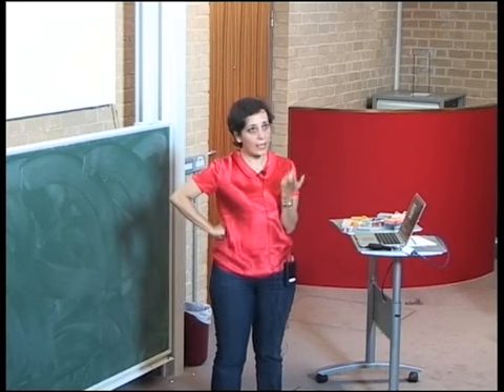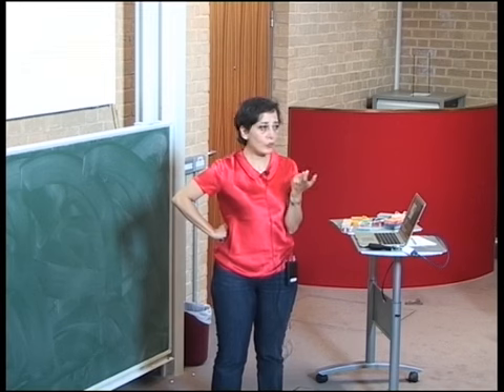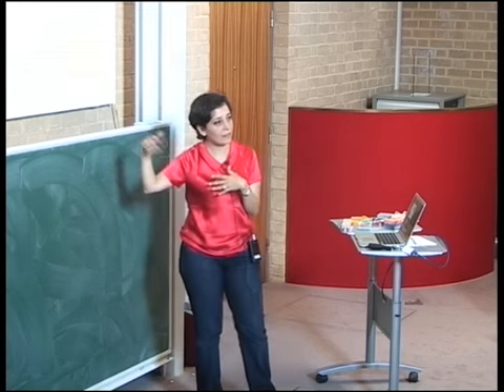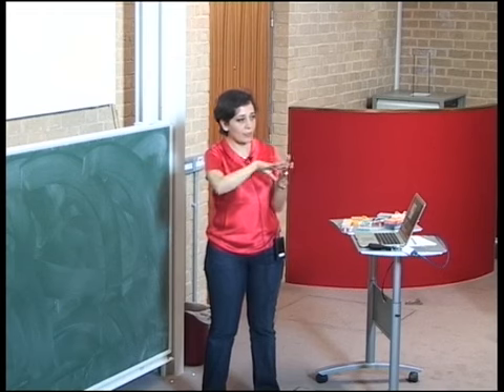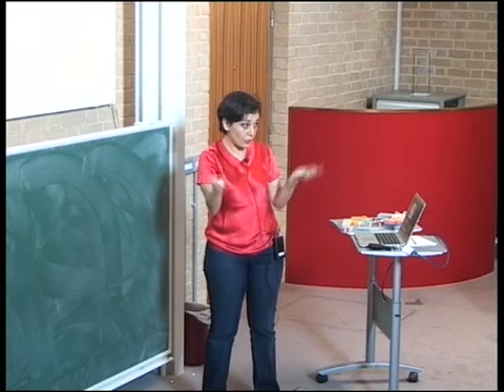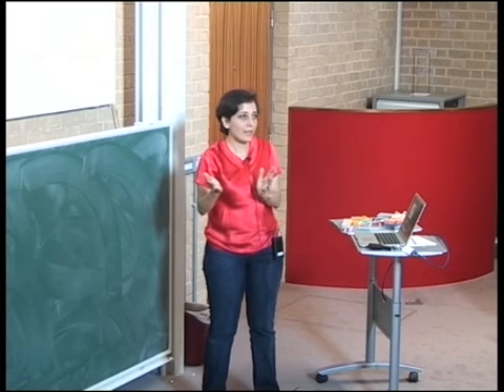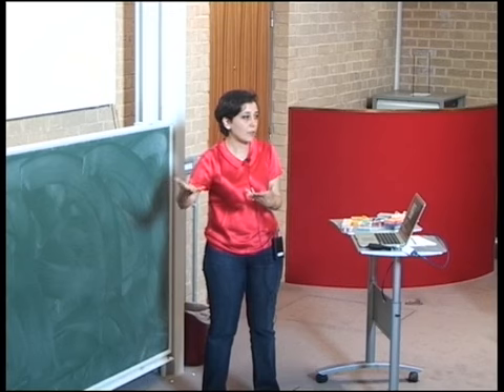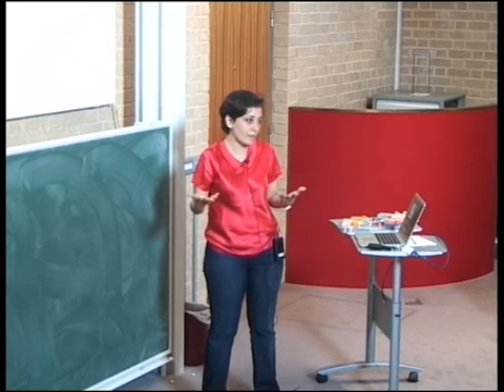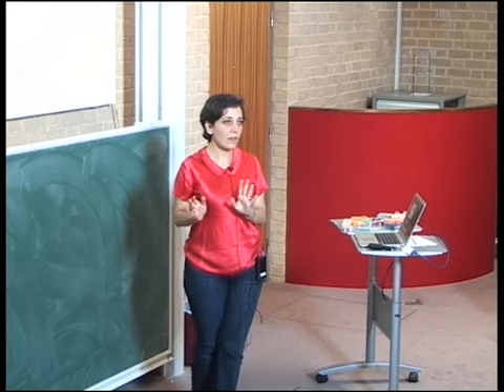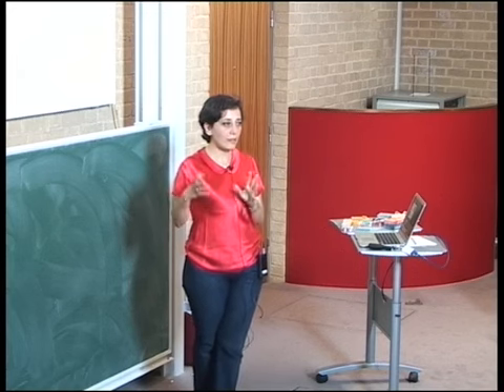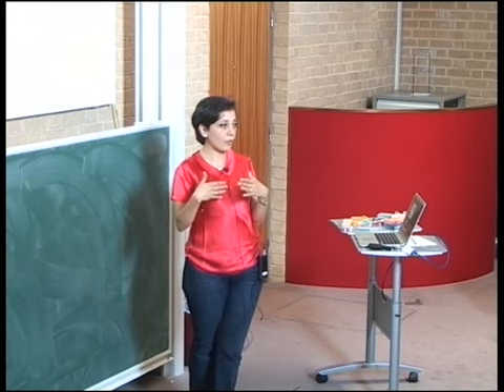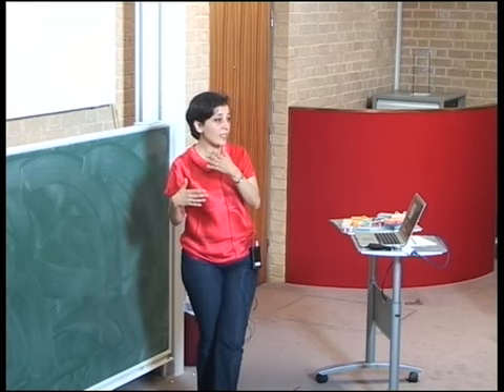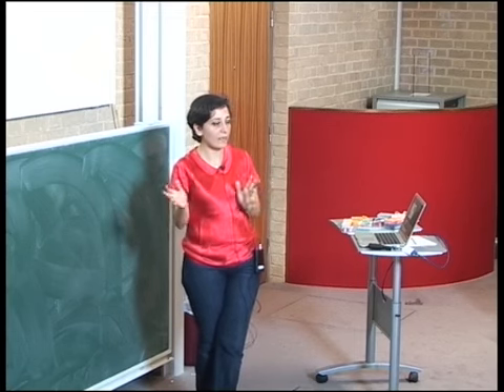Okay, on one hand, I think it's also interesting because from the simulation point of view, this tells you that the rate and the progression of the decrease of what you measure in the shape is actually a lot related to the fact that you develop these defects, and you can imagine that these defects control exactly the elastic properties of the interface, for example, buckling. One thing that we are trying to do is a lattice-Boltzmann simulation in which you have the lattice-Boltzmann for the two fluids, and then you have the colloidal particles at the interface, and like that we have a 3D system in which we can, for example, look at this type of thing.